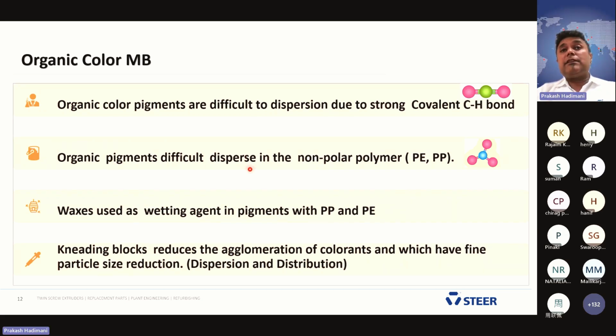Organic pigments are also difficult to disperse in non-polar polymers. Who are those? Polyethylene, polypropylene. These polymers are non-polar. To make the non-polar polymers and the pigments compatible, we need to use wetting agents or waxes. Why do you need waxes? Because dry pigments have a tendency to re-agglomerate, because when they are exposed to moisture, they try to re-agglomerate.